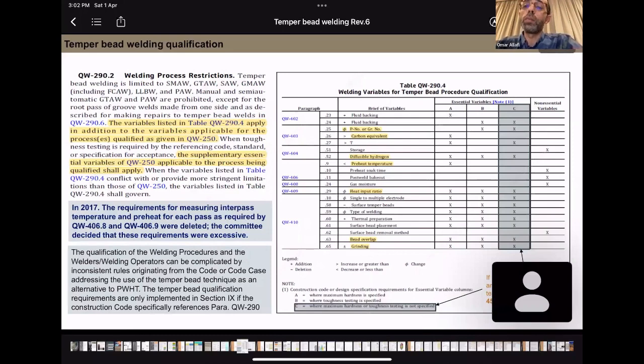So these essential variables, in addition to the essential variables in QW-250, are required and mandatory to be followed. So when impact testing is required, the supplementary essential variables are also applicable for the qualification. So in QW-250, you have the supplementary essential variables and the essential variables. And we know that when impact toughness is required, the supplementary essential variables become essential. So all this is also mandatory. But we need to keep in mind that when variables listed in this table conflict with or provide more stringent limitations than those in 250, the variables listed here shall govern.